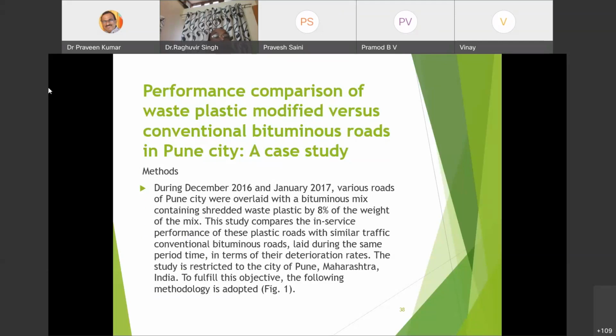A case study for Pune city is here. During December 2016 and January 2017, various roads of Pune city were overlaid with a bituminous mix containing shredded waste plastic at 8% by weight of bitumen. The in-service performance of these plastic roads was compared with similar-traffic conventional bituminous roads, that is, with 80/100 grade bitumen or VG 10 grade bitumen, laid during the same period of time, in terms of their deterioration rates. The state is Maharashtra, India. To fulfill this objective, the following methodology was adopted.